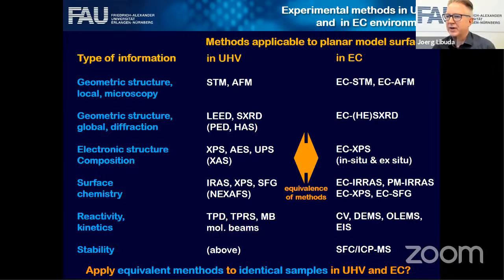But contaminations are always a problem. It's a problem in any kind of transfer, not only in electrochemistry, but also in principle with all kinds of high pressure experiments in catalysis, so people trying to do near ambient pressure spectroscopies and methods. If you go to ambient pressure and have ppm contamination, you can have monolayers easily. And that's an intrinsic problem.